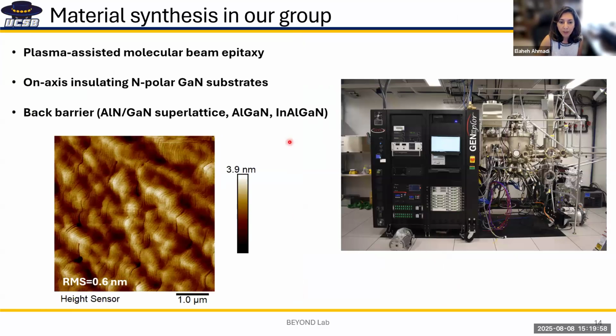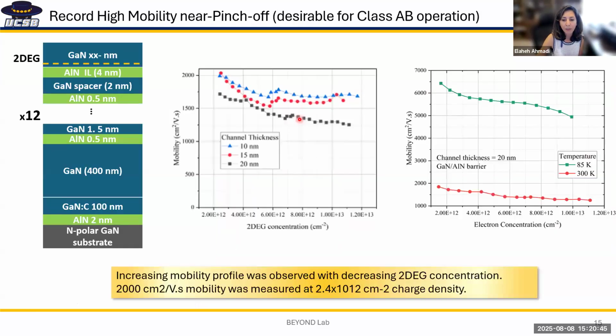Now, coming back to what we focused on, MBE growth. All of our efforts have been on nitrogen polar bulk GaN, and this is basically the typical surface morphology that we get on our nitrogen polar GaN HEMT structures. We have looked at different back barriers: aluminum nitride, gallium nitride superlattice, AlGaN, indium aluminum nitride, and now, as part of this new effort that we have with EMI Commons through California Dreams, we are looking at alternative barriers like indium aluminum gallium nitride quaternaries and aluminum scandium gallium nitride, and we have some preliminary results on those.